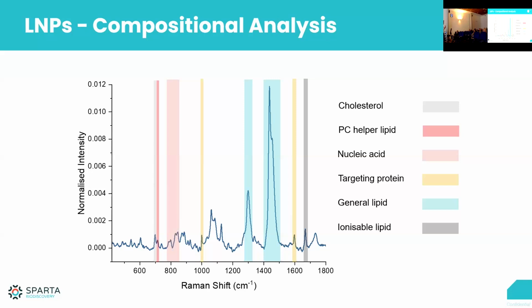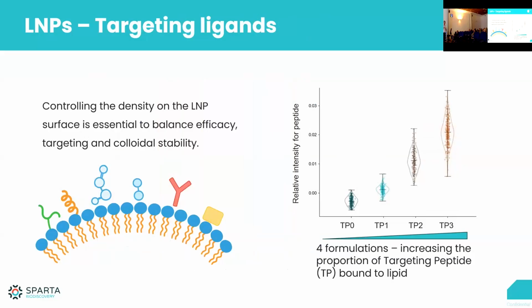So it's not like NMR or like HPLC, where you really have to look at every little squiggle and see what is this, what is this, what is this. You can't do that as an academic exercise. It's fun if you like that, but for day-to-day use, we don't have to do that, because, for instance, for cholesterol, we look at the peak at 700, which is very characteristic for cholesterol, and we can look at the variation in that peak to look at the variation in cholesterol content. So it's really looking at specific marker signals that we then analyze in a univariate analysis way. So we go basically away from this Raman spectrum and really look at specific variations of different components. So there's a database in the software that helps you drop that in.